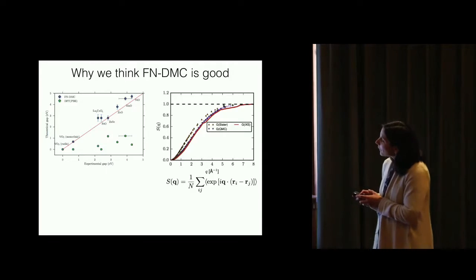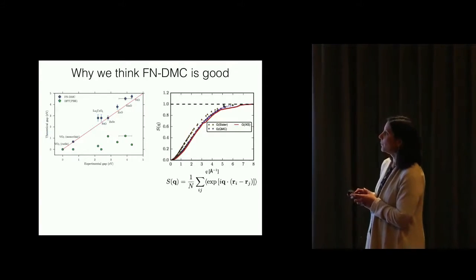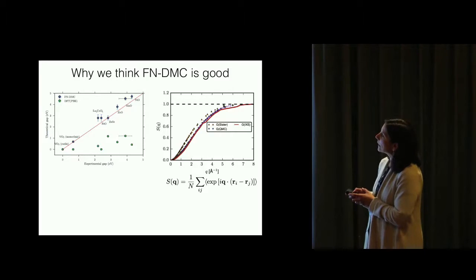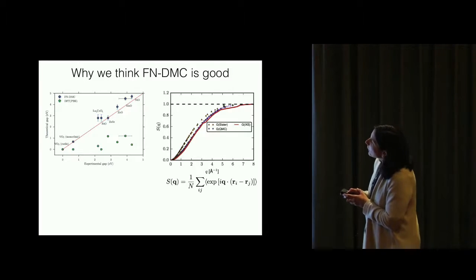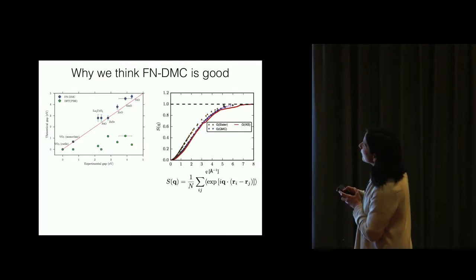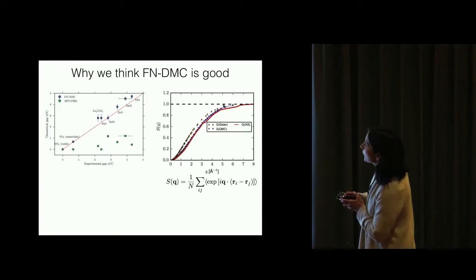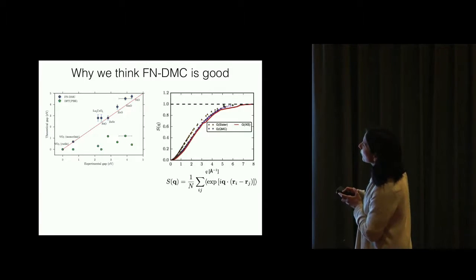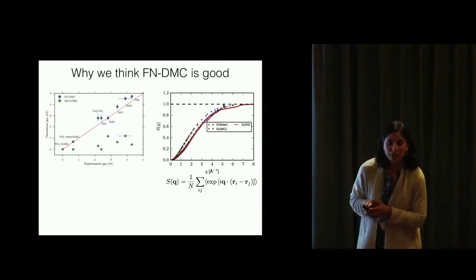We can actually calculate properties that can then be measured in an experiment. So here's an example of the structure factor that's been calculated for graphene. So the color turned out a little bit funny here, but this line here towards the bottom is from inelastic X-ray scattering. This triangle comes from the Slater determinant description, and then what's here, coming into much better agreement with experiment, is the quantum Monte Carlo description of that structure factor as well.